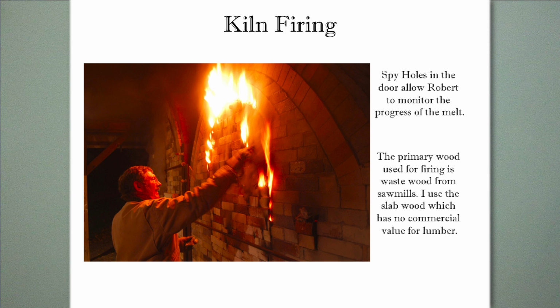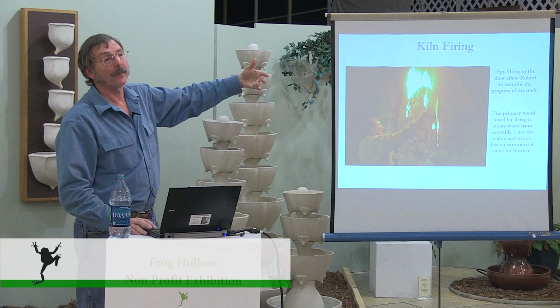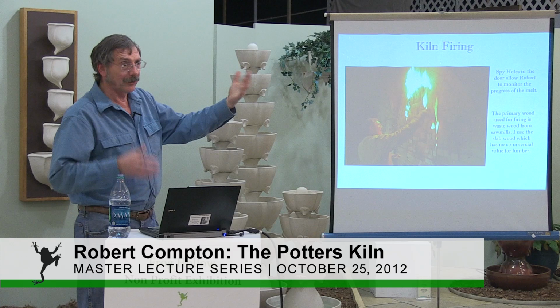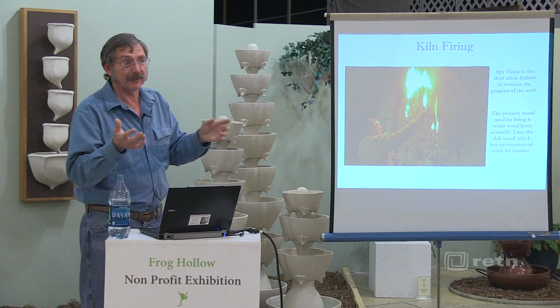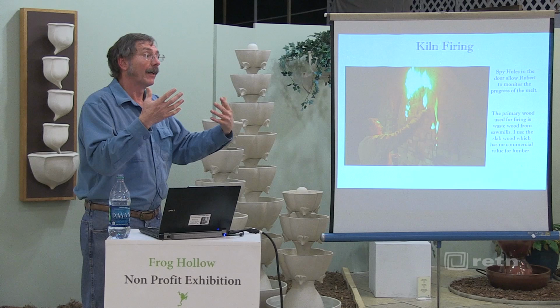I'm basically monitoring through spy holes. I have three heights, top, middle, bottom, front and back of each chamber. So I'm looking at least 6 cone packs in each chamber for height variation in temperature. And I try to adjust that temperature with the kind of wood we fire with, that is what species to some extent. Hardwoods are denser, they don't burn as fast. Smaller diameter wood burns faster, so you get a different kind of flame.